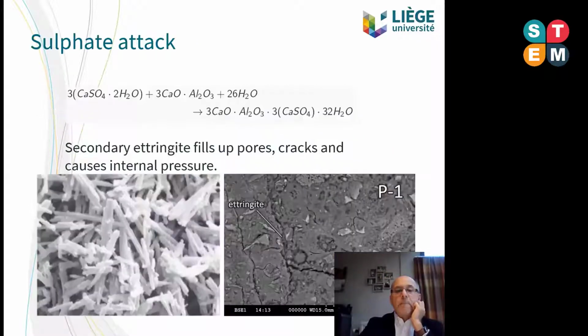Why is it so important? It's because the chemical reaction of this gypsum with the calcium aluminate you can find in the cement, in presence of water, can produce big crystals in the form of ettringite, and this secondary ettringite, which is produced by this chemical reaction, is producing expansion cracks, and